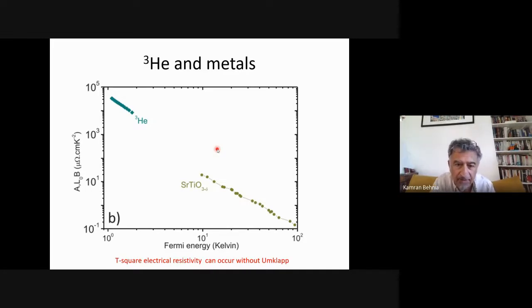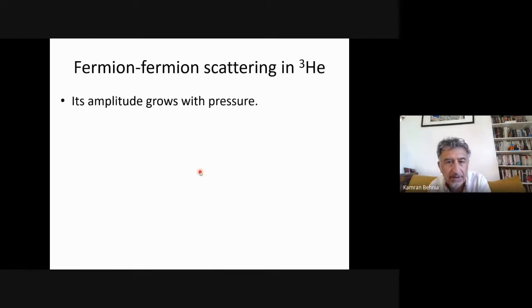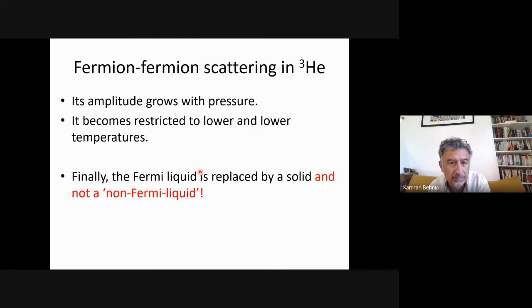Now, if I go one bit further and I show the variation of this term in helium-3 and in strontium titanate, you can see that again, there is the same tendency. The Fermi energy in strontium titanate is small, but of course is larger than helium-3. You see that the slope is not exactly the same, but you see that the two physics are going to meet again. So this brings us to this idea that what drives T-square resistivity in helium-3 and in metals should be related to each other. And we should have in mind that in the case of helium-3, this Fermi liquid is not replaced by a non-Fermi liquid, it is replaced by a solid.